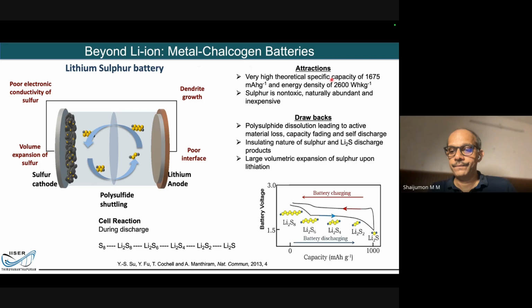The capacity is quite high, 1675 milliampere hour per gram, and energy density is almost 10 times what we can get now. Remember, the existing lithium-ion battery has an energy density of about 250 watt-hour per kilogram, whereas if you use a sulfur battery system, it is going to give you something like 2600 watt-hour per kilogram, which is absolutely exciting to work in this area, right?